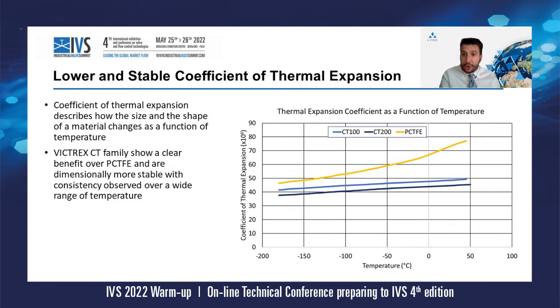In this slide, it's shown the second biggest advantage of using CT100 or CT200 instead of PCTFE. So both the materials have in fact a lower and almost constant coefficient of thermal expansion, not only at the very low temperature, but especially as the temperature goes up. So the difference becomes more and more evident when the temperature goes up. The graph shows data only up to 50 degrees. The gap at higher temperature can just increase.